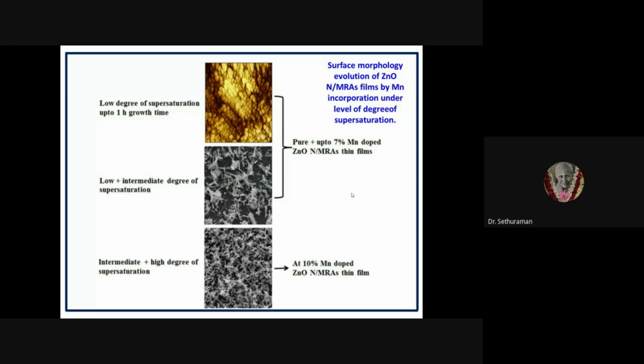From this work, we found low degree of supersaturation up to 1 hour growth time, low plus intermediate degree of supersaturation, and intermediate plus high degree of supersaturation. With low degree of supersaturation at 1 hour growth, and low plus intermediate degree of supersaturation, we successfully grew zinc oxide nanorods as well as zinc oxide nano micro rod assembly thin films on the surface of the glass substrate. But when we increased the doping concentration to 10%, we found that the nanorods decreased completely, and we converted the surface into a micro assembly. Surface morphology evolution of zinc oxide nano micro rod assembly array films by Mn incorporation under different degrees of supersaturation.